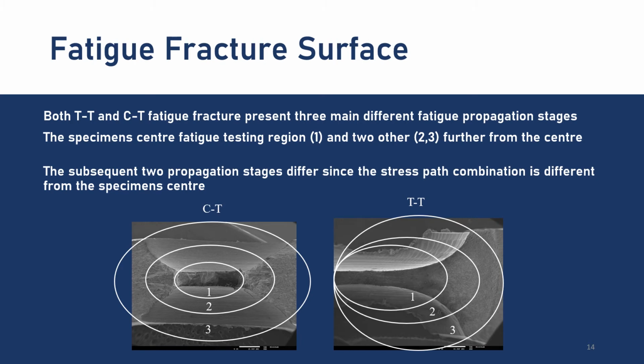Now, having access to the fatigue fracture surface and making a SEM analysis, we first make a general observation of the fatigue fracture surface. We can clearly see there are three stages of propagation. The first one, and the one of main interest, happens on the small cross-section area of the specimens. This is where the stress combination is the desired one of study, and this is where we're going to make a deeper analysis.